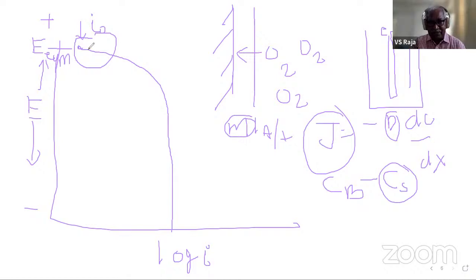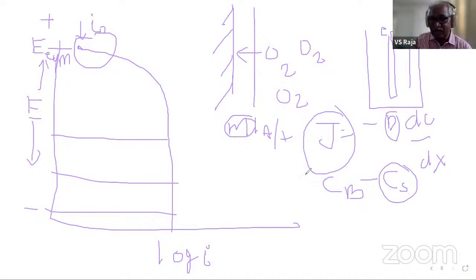So when I keep increasing this potential, the current increases. Why does it increase? Because there's a driving force. Please see, you are applying a driving force. Eta is nothing but a driving force. So as the driving force is increasing, the rate of reaction is increasing. But then beyond a certain level, everything disappears. Nothing is there on the surface now. The moment it comes, it's done. So if I increase further and further potentials, nothing happens because the surface concentration already reached zero here. Here also zero only. So that means it reaches the maximum current. And now it is 100% controlled by the diffusion process. But this depends upon the D value.